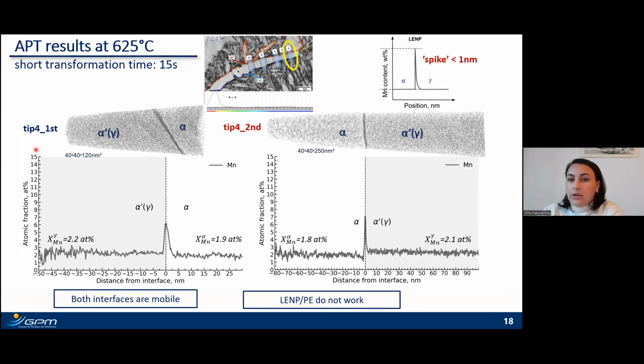The first thing we can say about this result is that we can without any doubt reject the para-equilibrium assumption in this case, because instead of a flat profile of manganese through the interface, we clearly observe manganese segregation at both interfaces, which can also mean that both interfaces are mobile. But now the question is whether the observed manganese peak can be treated as a manganese spike. Of course, the experimentally observed width is significantly bigger than the expected one for the manganese spike, but the peak width measured by APT can always be argued by the spatial resolution, so we cannot compare this parameter.